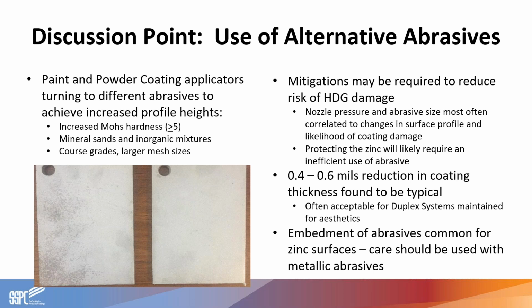But one thing to consider in your conversations with the coating applicator is that the blaster will need to know that you are aware that these types of measures used to protect the galvanized coating are going to require a significantly inefficient use of the abrasives, and they may not be used to that type of requirement. Generally speaking, in our investigations as well, we found that when using these types of harder, larger abrasives, 0.4 to 0.6 mils reduction in coating thickness may be somewhat typical.